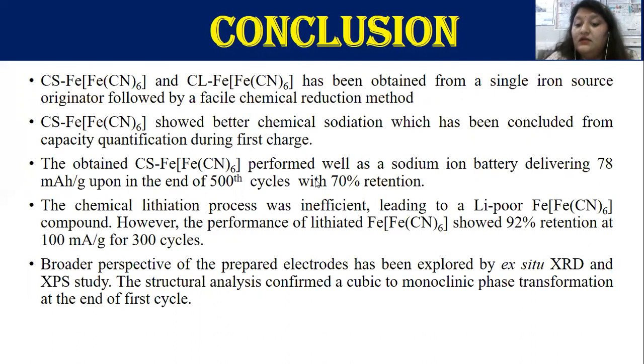The obtained CSFeFeCN6 performed well as a sodium ion battery, delivering a capacity of 78 mAh per gram upon completion of 500 cycles, about 70% retention. Nevertheless, the chemical lithiation process was inefficient, leading to a lithium poor FeFeCN6 compound. However, the performance of lithiated PBA was better and delivered a retention of 92% at the end of 300 cycles at a higher current density of 100 milliamperes per gram.